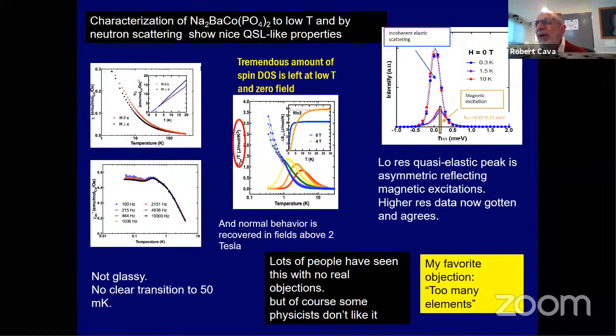And cobalt is a bizarre 3D element. So I guess I was trying to look that up, but I recommend you look it up too. In the transition series, we always say that the orbital contribution to the angular momentum is quenched for the 3D elements because the interactions with the ligands are too strong. But cobalt is an outlier. It has a strong spin orbit coupling term added to its magnetic moments. So cobalt is a bizarre case anyway, and I think it's just been ignored for too long, but that's my personal opinion. And there are some interesting characteristics that they found.